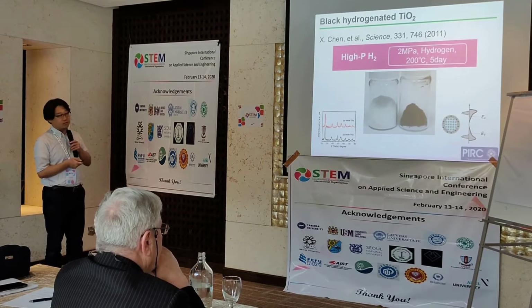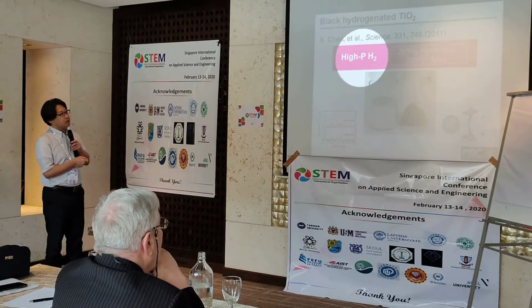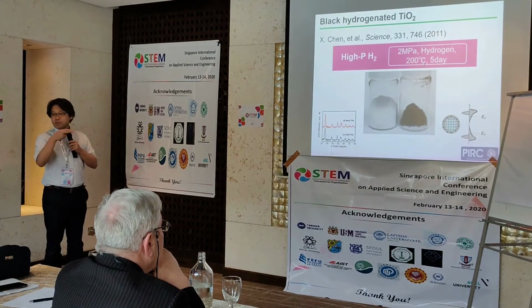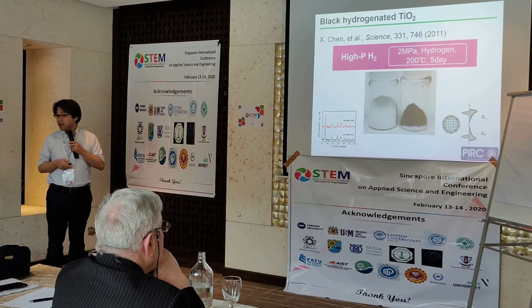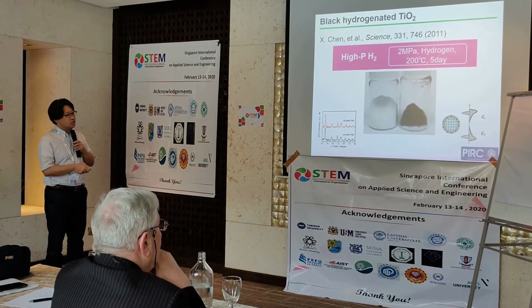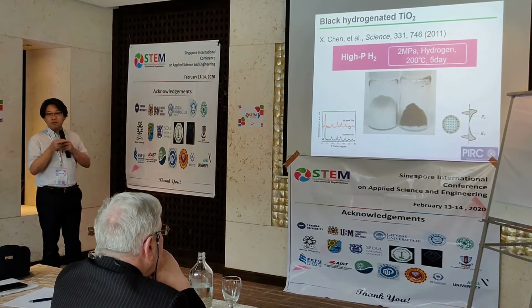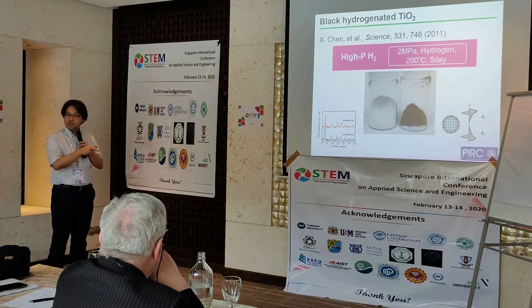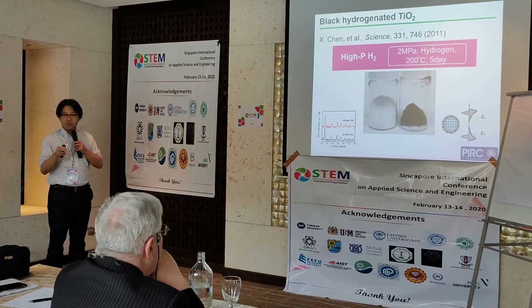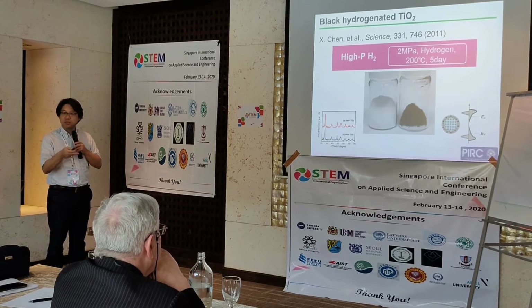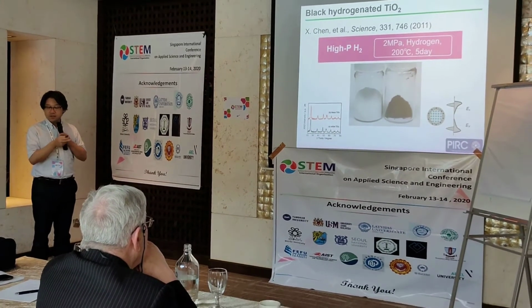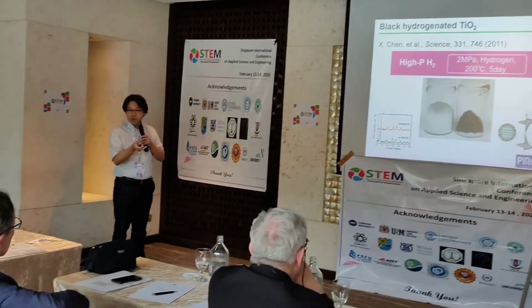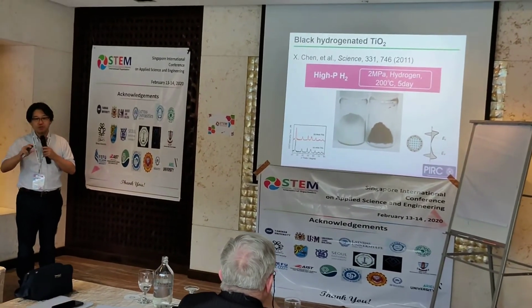But in this case, it needs high pressure hydrogen at high temperature, 200 degrees, and it takes a long time, 5 days. Then this white material changed to a black one. Then they checked the XRD spectra. Before and after this treatment, the XRD spectra are not changed. That means only the subsurface is changed, with oxygen vacancy. Then the color is changed. The bulk material keeps the anatase, the same structure.